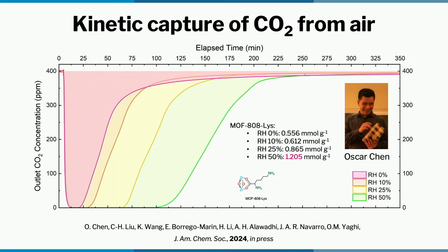Of course, it takes up a little bit of water as well. You need it. And it stays in the pores, and then when all the amines are saturated, CO2 comes out. So this means that I can separate CO2 from air with 1.2 millimole per gram capacity, which is really above what is required if this material can cycle 100,000 cycles. Well, it turns out that in this experiment, this material cannot cycle more than 500 cycles because although it's stable in water and acid, it's not stable in base.